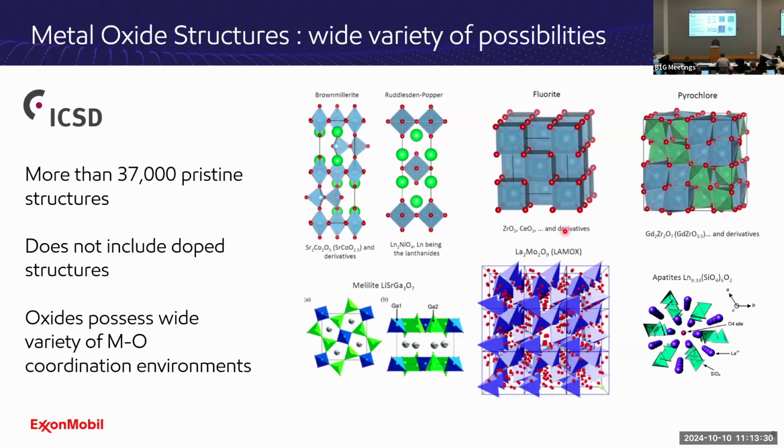If you read papers where they have measured the diffusion barrier of oxygen in a material, something like lanthanum aluminate, if you actually read the paper, it's like, well, actually they put in a little bit of fairy dust in order to generate the vacancies, in order to actually be able to measure a transport rate. Because otherwise, if you have something where you have two irreducible cations like lanthanum aluminate, the graduate student would spend their entire career making one measurement.